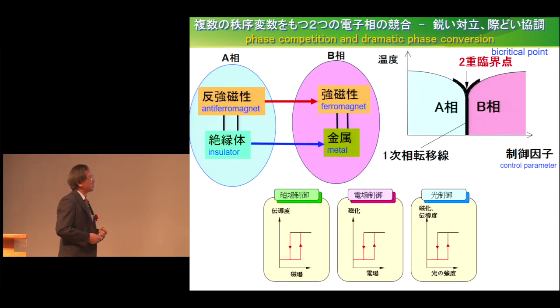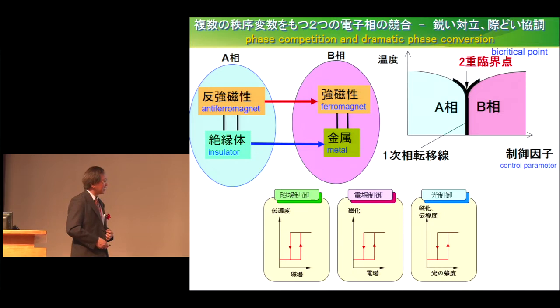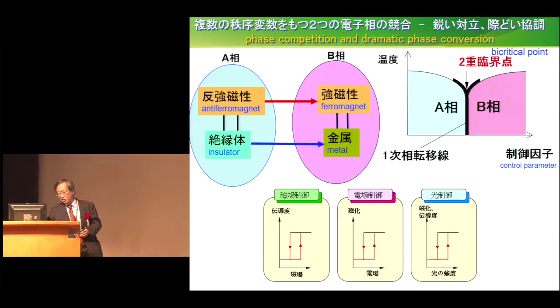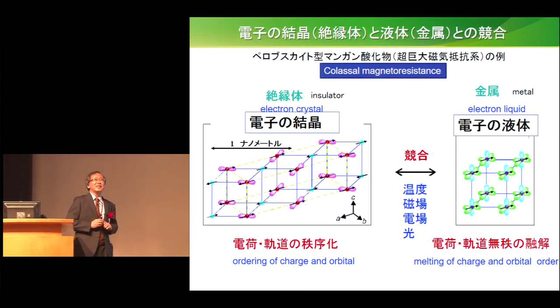This is what we call a bicritical point. From A to B, with a small stimulus, the phase changes from A to B. That means it is a change from insulator to metal, and that accompanies a change from anti-ferromagnet to ferromagnet, with external light or magnetic fields. To give priority to the ferromagnetism against the anti-ferromagnetism, then the insulator will instantly change to metal. This shows you the change of the electric conductivity with the control by the magnetic field or the light, which turns the material into a magnet or the metal.